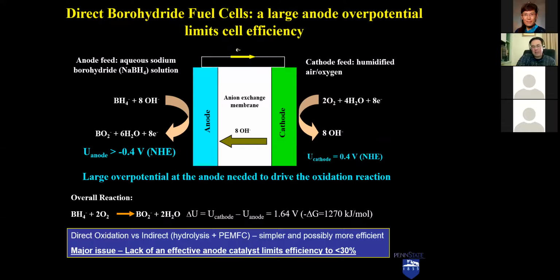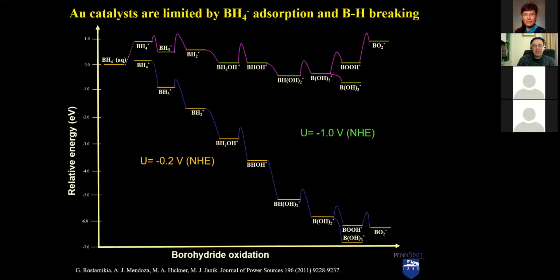And we have looked at catalyst development for this reaction. The reason I bring it up is because I want to convince you that we can look at complex mechanisms that aren't hydrogen going on and off a surface. So this starts all the way at a BH4 anion in solution and ends all the way at that borate. And we actually also looked at the hydrated borate as products. We get a number of elementary steps, but if you can calculate activation barriers, then you can see how these rates vary with voltage.